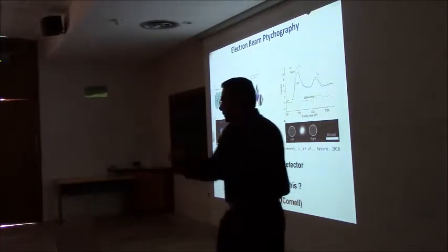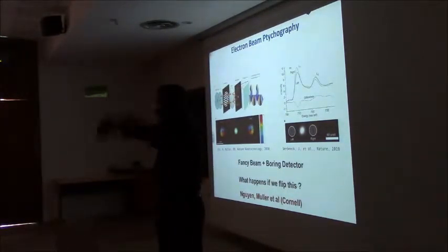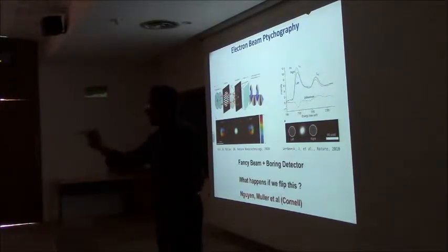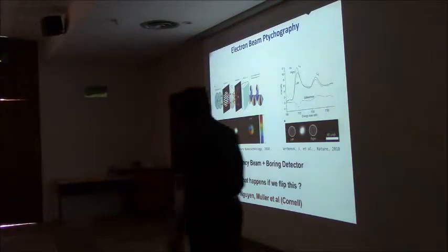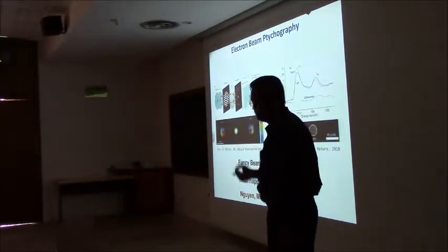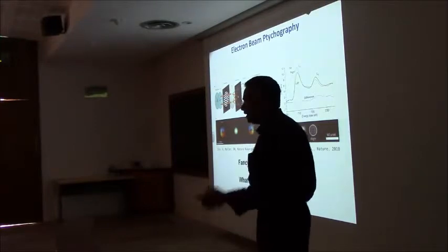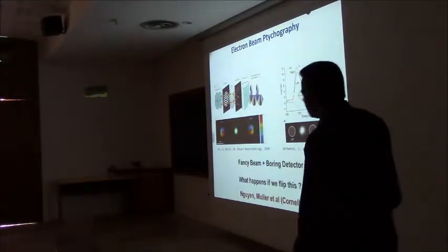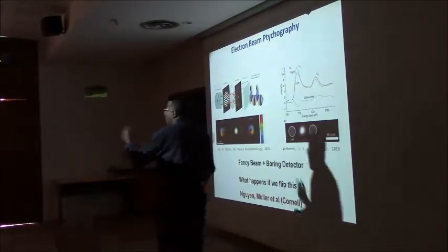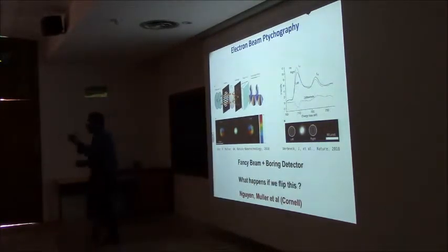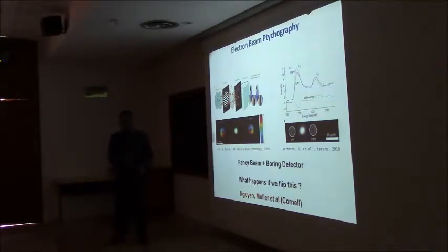Typically the electron beam in a microscope is a parallel beam, but there's nothing that says I cannot make it a spiral beam. You can put zone plates, like they do here, and create a spiral beam. And this paper, this is one of the papers, and the Schattschneider paper was a similar paper, where you can now, like you would do with X-rays, circularly polarized X-rays, also have circularly polarized electron beams. And you can do circular dichroism measurements. The absorption of light, in this case electrons, in a ferromagnetic material would be different depending on the helicity, whether it's going this way or this way. And that's what this experiment is. And the difference between them is a dichroism.